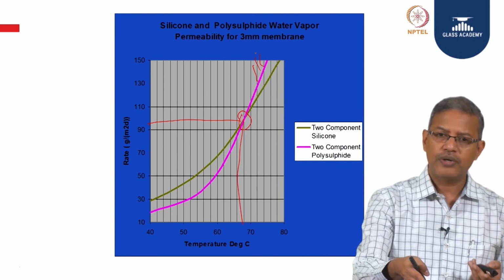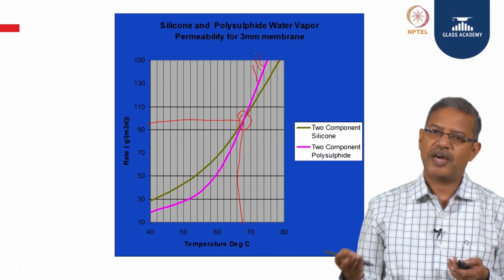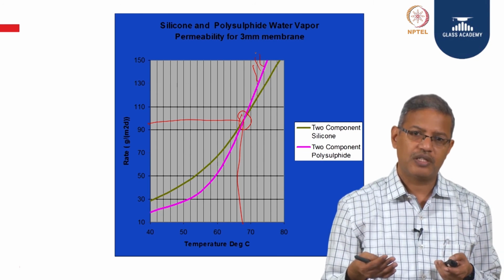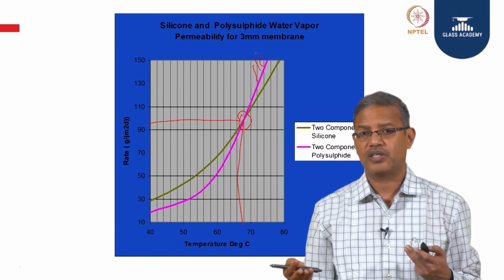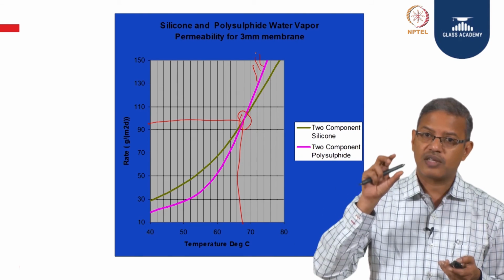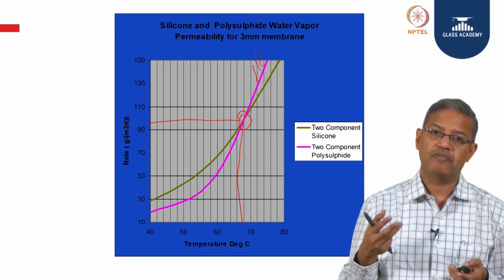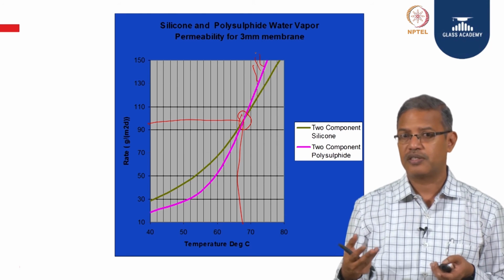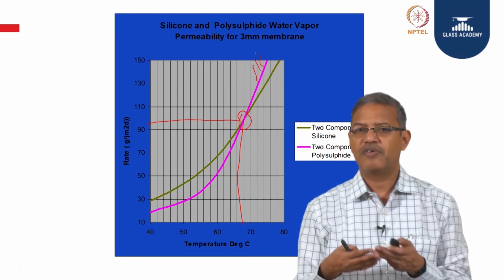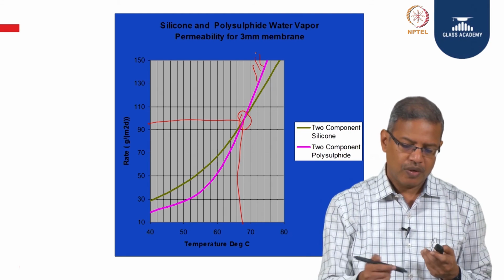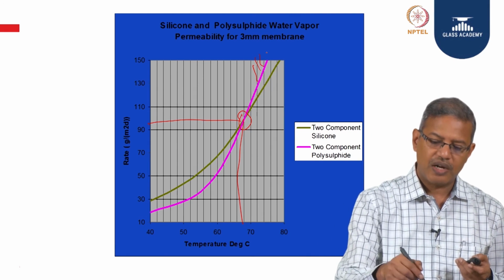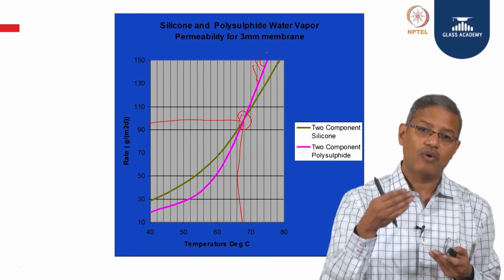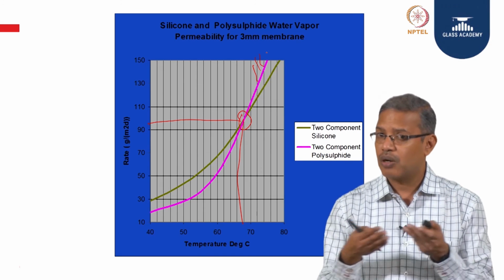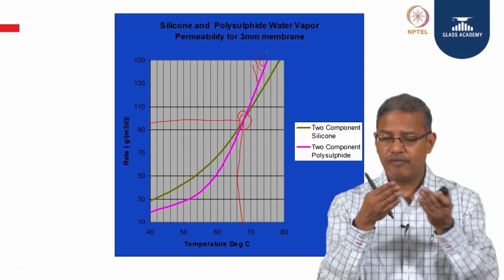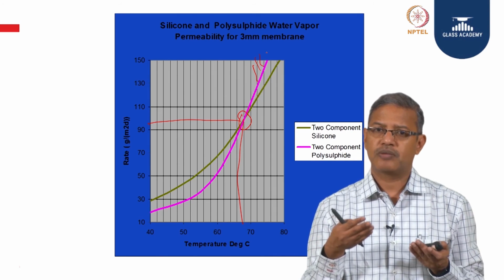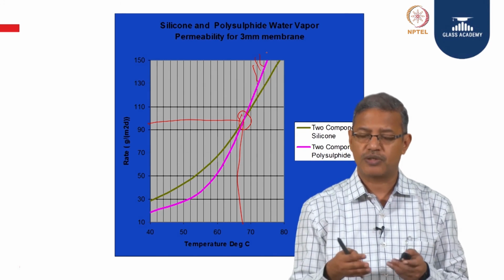This is not unusual. If you have an air temperature of 30, 35 or 40 degrees, which is very common in India and multiple locations, the surface temperature of the glass really goes up very high. It could be a 20, 25, 30 degree difference. So, 65 is not very uncommon, it is very common in India. So, you tend to see that the organic system has already taken over from silicone, because silicone, as I mentioned to you, shows very minimal variation in properties because of climatic and atmospheric conditions.